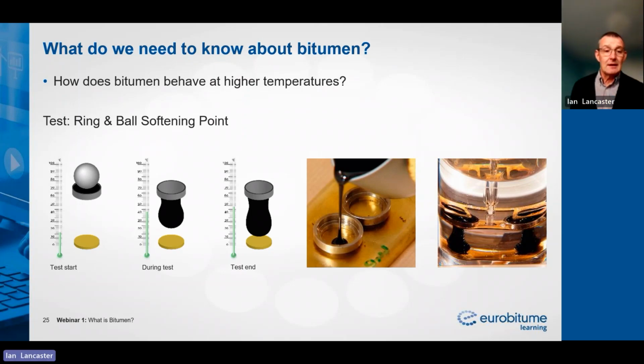It involves filling 2 rings with a precise amount of bitumen, allowing those samples to cool down, and then any excess is removed from the surface of the rings. We then cool those 2 rings down, transfer them into a frame, which you can see here, mount the frame into a beaker and place the beaker onto a heating device. And then we increase the temperature of the beaker at a very precisely defined rate of 5 degrees per minute.